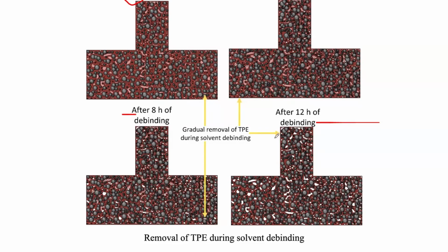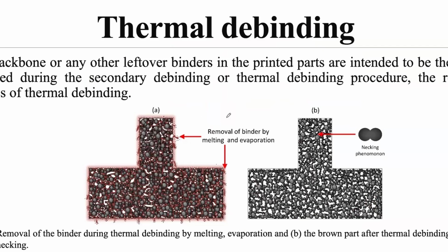So when I put it into the sintering furnace in the next step, you see everything has come out, and you get a structure. At the same time, you see this necking phenomenon also happening in thermal debinding, where the powders are coming together and joining together. Now you can certainly say that this process looks like there will be some porosity. Yes, there will be some porosity that will remain, and that porosity is comparable to the porosity that you get in the LPBF process. But there are ways to tackle that porosity. We are also working on post-processing methods. We are working on hot isostatic pressing, which is a very good technique with which you can control these porosities that are appearing over here.